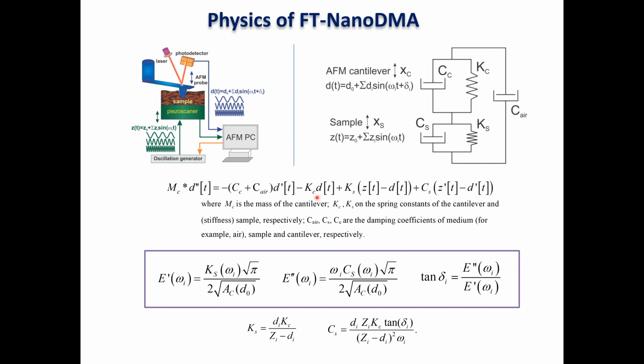So the physics of that is fairly straightforward. This is a forced harmonic oscillator. And when you crunch the numbers, you get these equations for storage modulus, loss modulus, and tangent delta, or loss tangent. So all these quantities are measured directly from the experiment, with the exception of the area. Area of contact has to be calculated from one of the contact models. And then all these coefficients can be calculated using either D, which is the amplitude of deflection of the cantilever, or Z, the amplitude of oscillation of the sample.